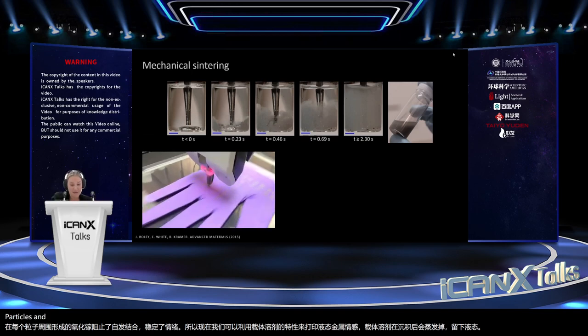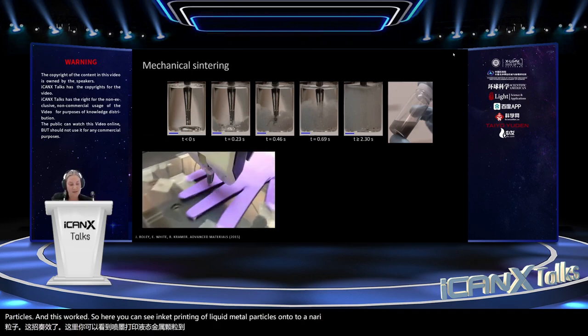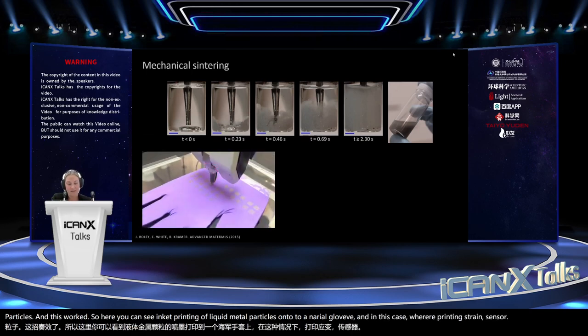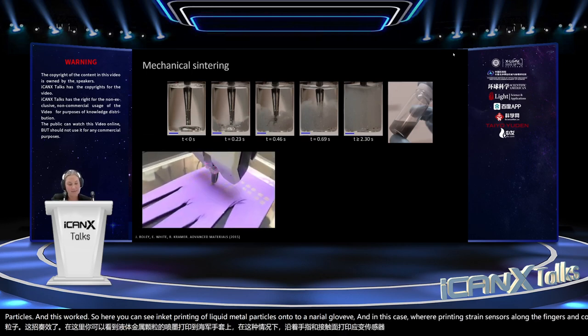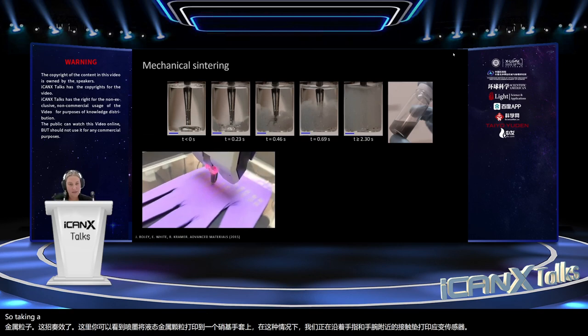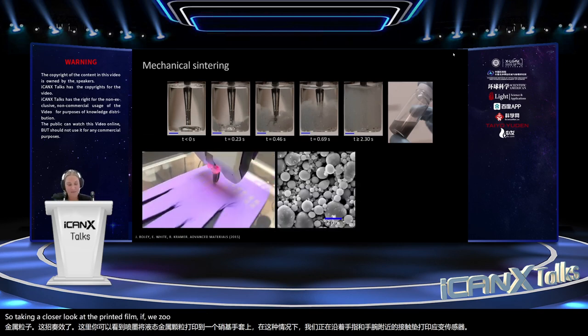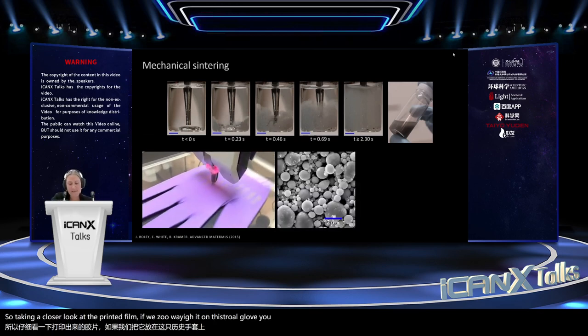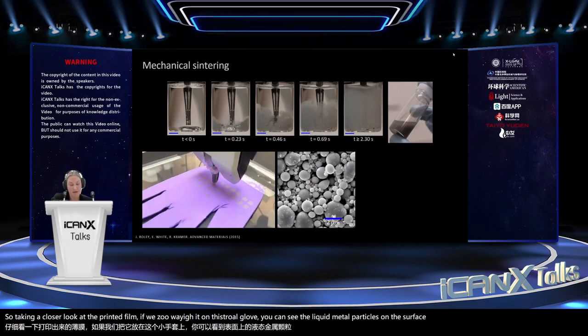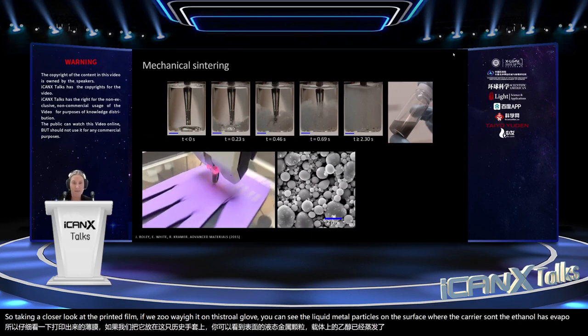And this worked. So here you can see inkjet printing of liquid metal particles onto a nitrile glove. And in this case, we're printing strain sensors along the fingers and contact pads near the wrist. So taking a closer look at the printed film, if we zoom way in on this nitrile glove, you can see the liquid metal particles on the surface where the carrier solvent, the ethanol, has evaporated away after deposition.